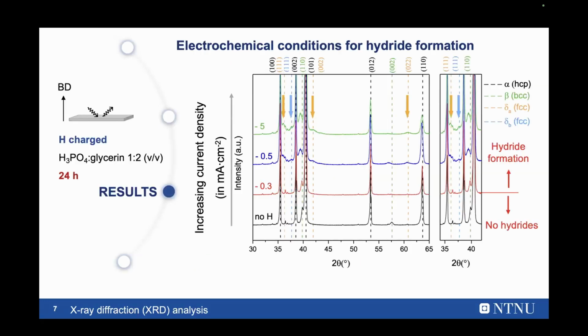So now coming already to charging the samples, throughout the presentation, the samples were galvanostatically charged in phosphoric acid and glycerin in 1:2 proportion, and the time was always kept constant, and the content of hydrogen was increased by increasing the current density. And to find the threshold where the hydride started forming, we saw that at minus 0.3, the hydrogen is still in solid solution, and by increasing it to 0.5 milliampere per square centimeter, we can observe the hydride formation due to the appearance of the peaks.